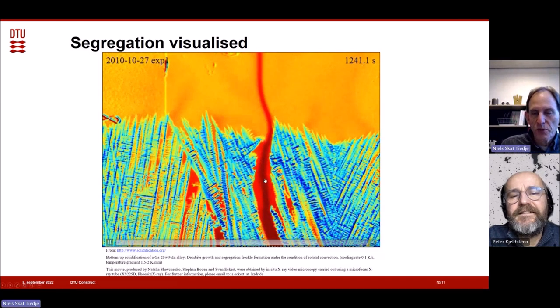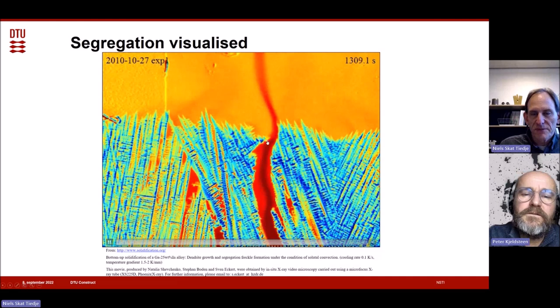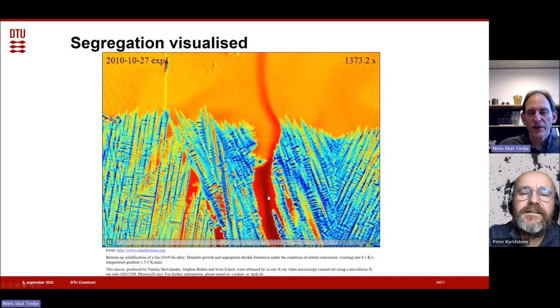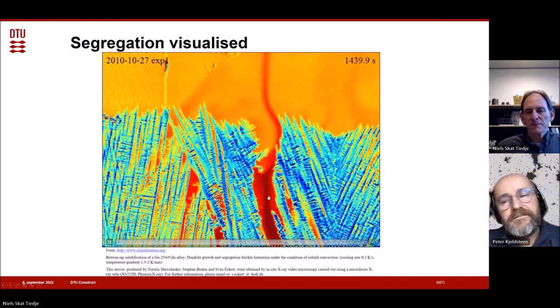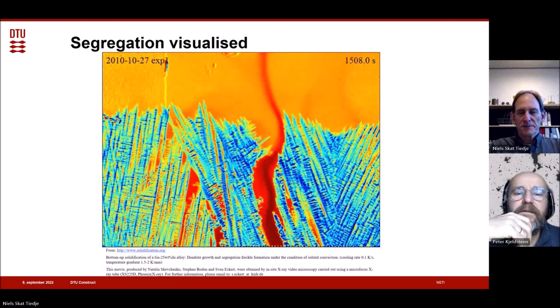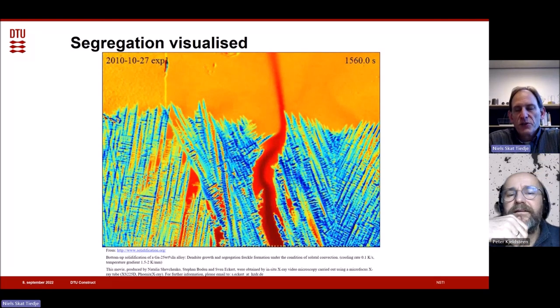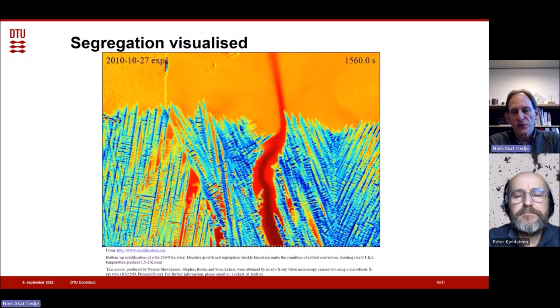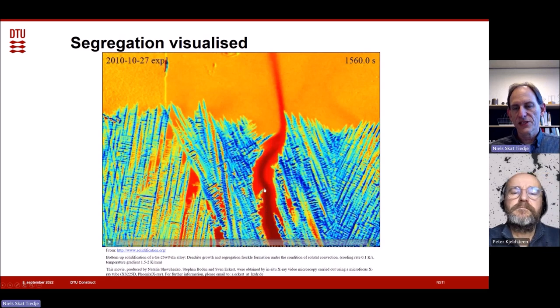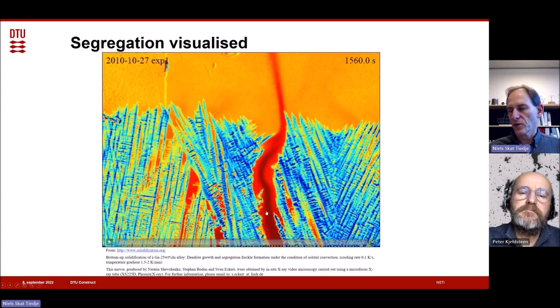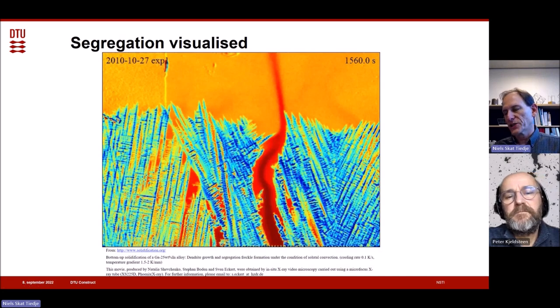And we see this plume of indium dissolving material. It's very, very pretty. So it's a video that shows the phase diagram, but it also shows some of the issues with solidification, because if you looked at the phase diagram, this should not be expected at all. But because we are pushing solute into the liquid, we are actually moving away from the phase diagram.